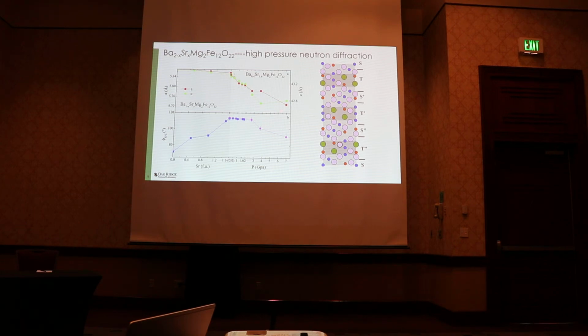So the pressure doesn't seem to make things quite better. What we can think about is, one, this maybe reaches a maximum, because it's three blocks, 120 degrees is probably the maximum. It's always staying in one unit cell. Another thing is maybe it's not just pressure in the doping, but also site disorder or other things.